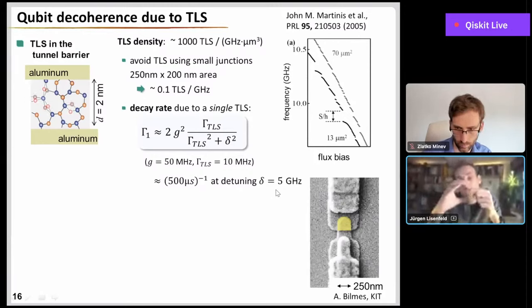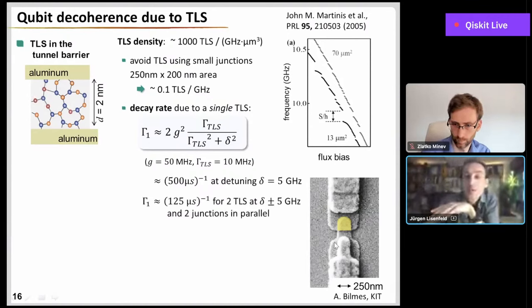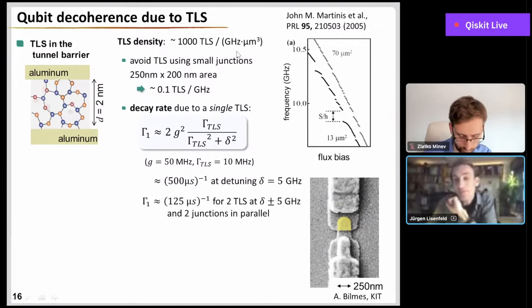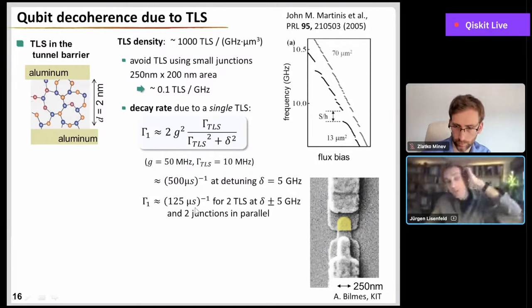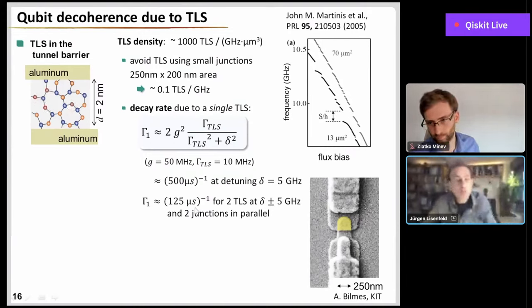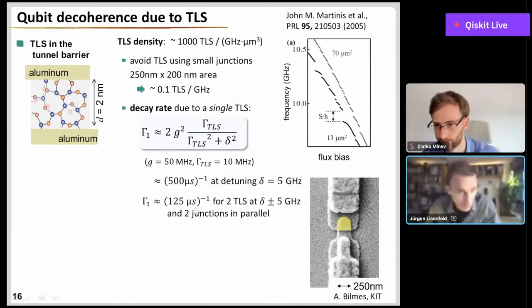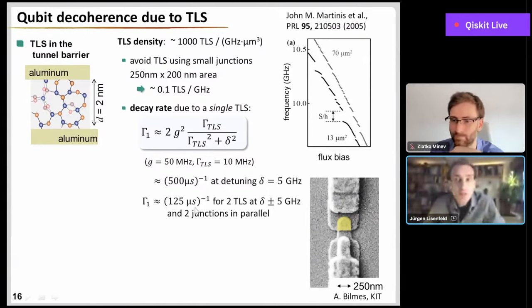And now you can imagine, if you take into account also the second defect on the other side of the 5 gigahertz detuning, and also take into account maybe a second junction for having a tunable DC SQUID qubit, then you are already reduced to 125 microseconds for these two TLS at these current densities. And these 100 microseconds are already pretty close to values that we find if we are lucky and if you make really good qubits. So it's typical average values of the T1 time. And this may already be a hint that the defects may be one of the biggest reasons for these short